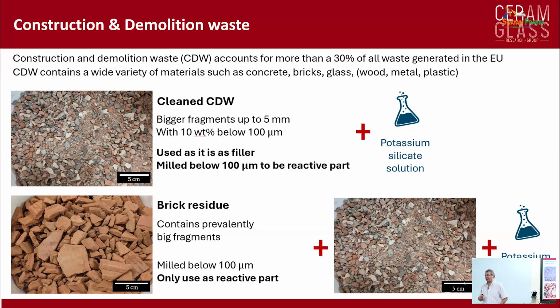Another work that we are carrying out is the use of waste material as a reactive source of alumina and silica. One possibility is to use construction demolition waste, which has issues in terms of being used again in the building industry. The characteristic of construction demolition waste, at least in our region, is that it contains some bricks or brick fragments. And of course, you're familiar that bricks are made from clay, so they're based on an aluminosilicate composition.